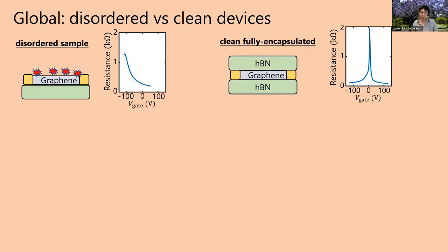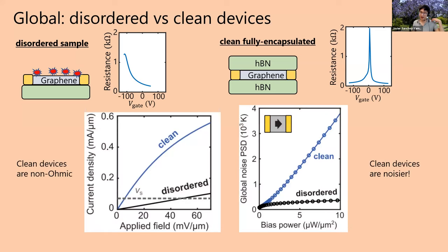What we're going to do is compare disordered and clean devices with each other. What was kind of interesting is that if you take the disordered device and the clean device and apply some electric field across them, this plot is the one we're going to look at. The x-axis is applied electric field, written here in terms of the power of the bias, and the y-axis is noise. What we found was that if you drive a graphene device and it's disordered, it doesn't generate much noise. It's actually pretty quiet. But if it's very clean, it generates a ton of noise.